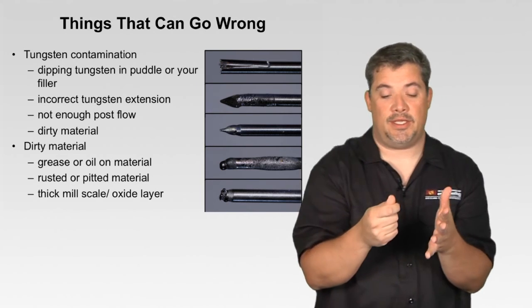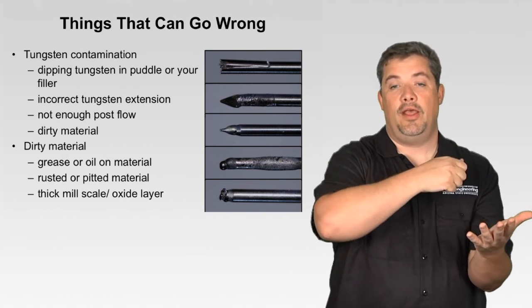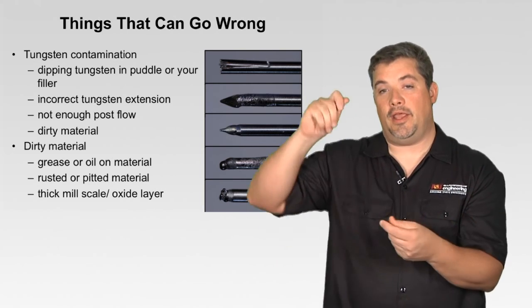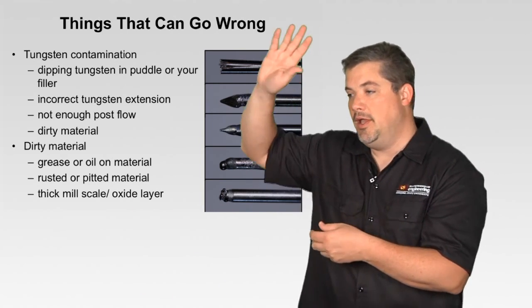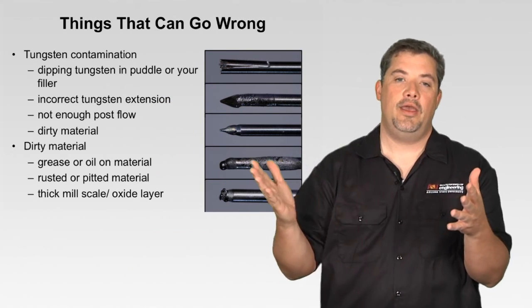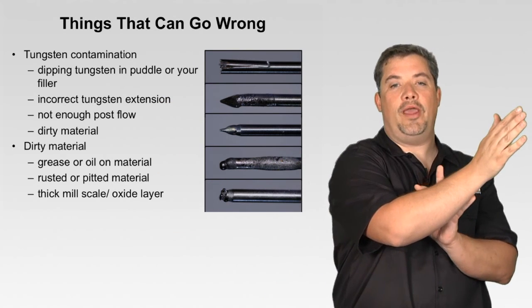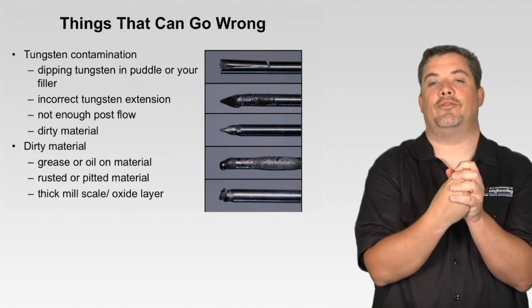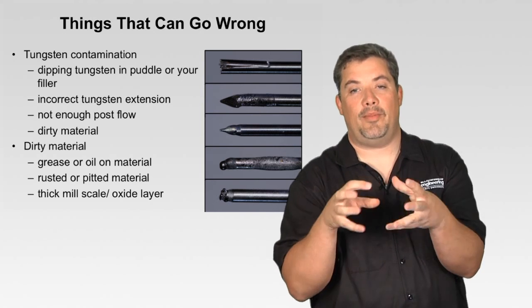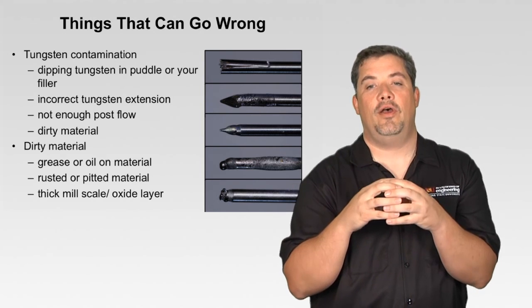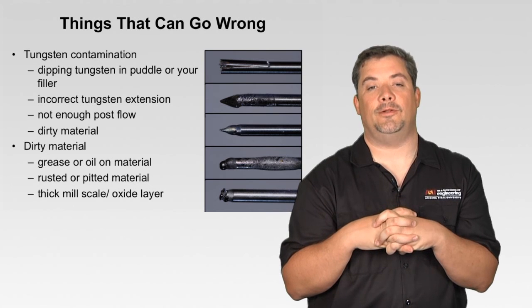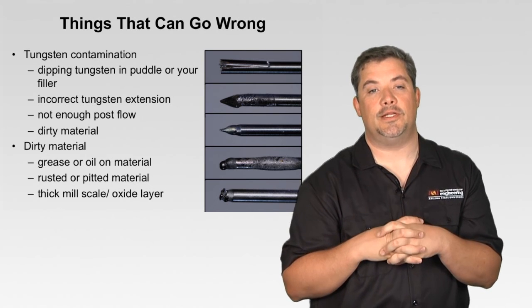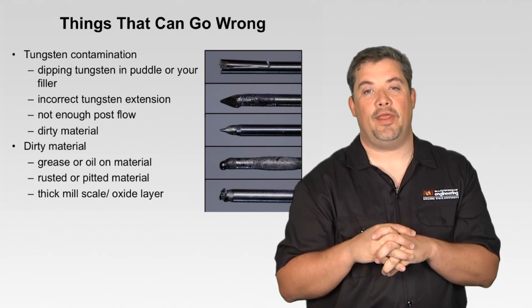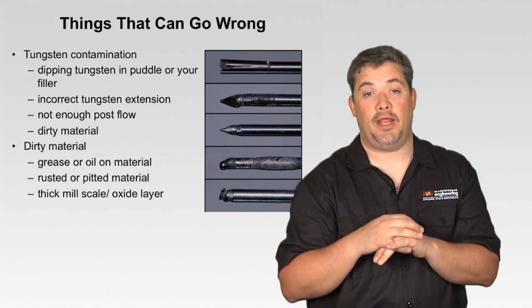Another thing that happens in TIG is we have such a low flow rate that people stop welding and drape their torch on something, and just the wind blowing by could cause the shielding gas to blow away for a moment and contaminate the surface of that tungsten. So you've got to make sure that tungsten gets cooled enough from the post-flow of that gas shielding to keep that tungsten intact. Dirty material is a bad thing that can cause contamination of your tungsten and your base metal.